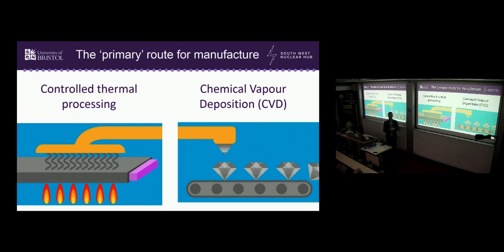on a substrate surface. Now, the quickest way to grow diamond is to grow directly on a diamond, but you can grow on other materials. Typically use things like tungsten or iridium. If you have an iridium single crystal, you will grow a diamond single crystal on top, in fact. And so we can grow a radioactive diamond layer very easily as long as we have a radioactive carrier gas. Now, of course, you can use a carbon-14 methane, but if you want to spice things up and increase the power output, you use a tritium plasma instead of a hydrogen plasma, and you incorporate tritium into the interstitial spaces in the diamond, and it's trapped there and can't get out, but it's beta emitting as well.